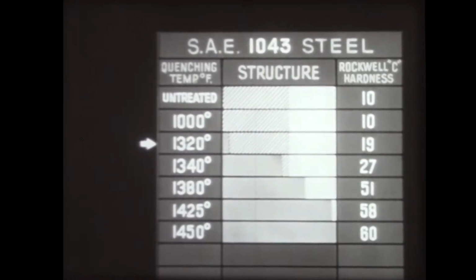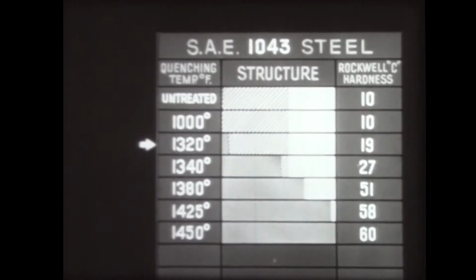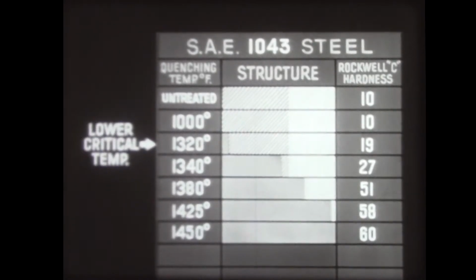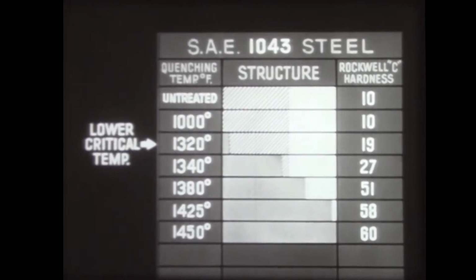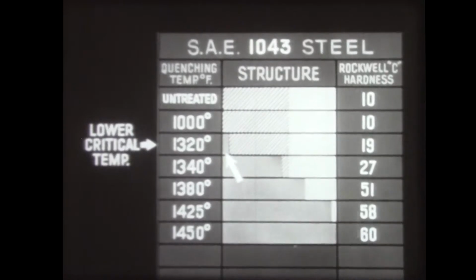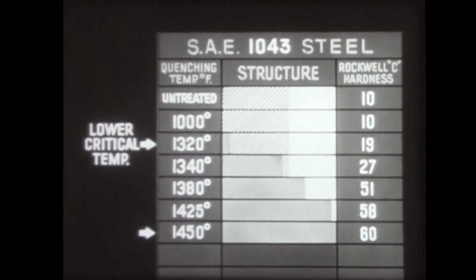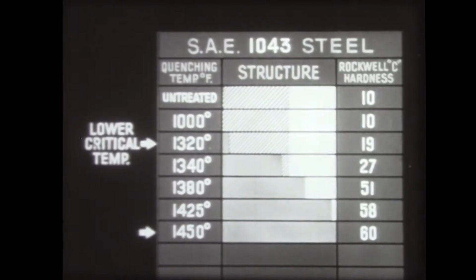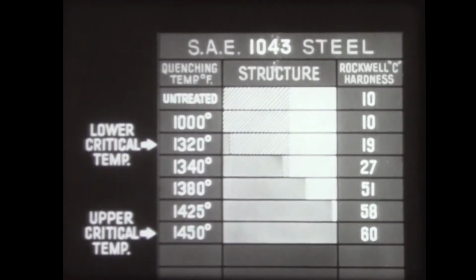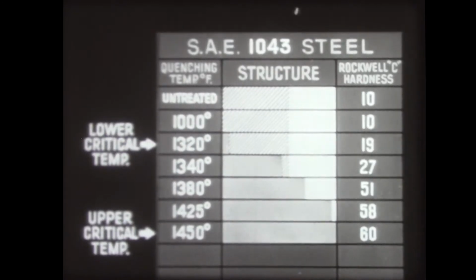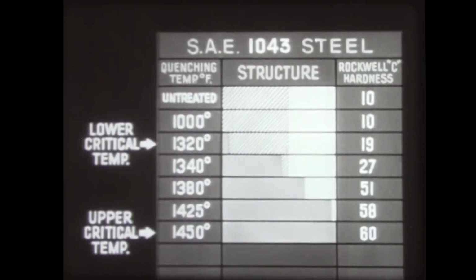Here is the point of initial hardening, 1320 degrees. This is called the lower critical temperature, the quenching temperature below which this steel will not harden. It was marked by the first appearance of martensite in the structure of the steel. Here is the point of maximum hardness, 1450 degrees. This is called the upper critical temperature of the steel. It was reached when the steel became entirely martensitic.